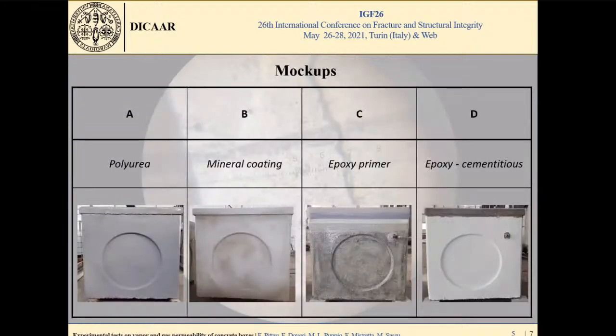So the 4 mockups that are presented here are characterized by 4 different coatings with different commercial material. You can read here: polyurea, mineral coating with different color, epoxy primer, and epoxy cementitious coating. Here there is the manhole for the alimentation by nitrogen, and the joint is sealed with different technology depending on the coating type.